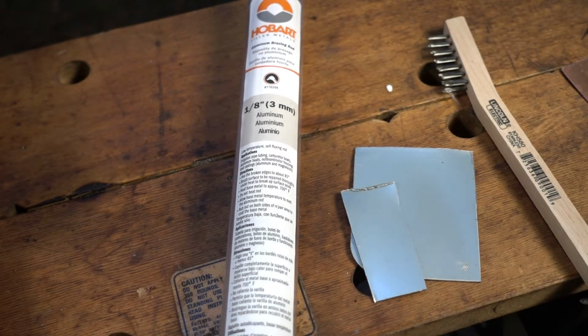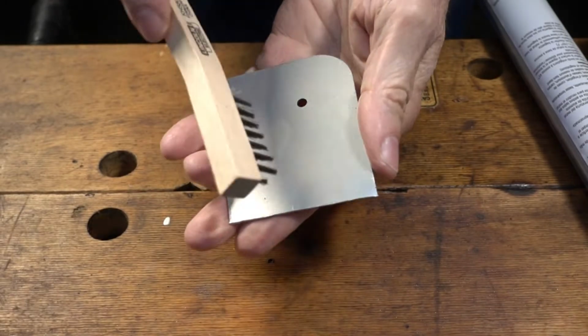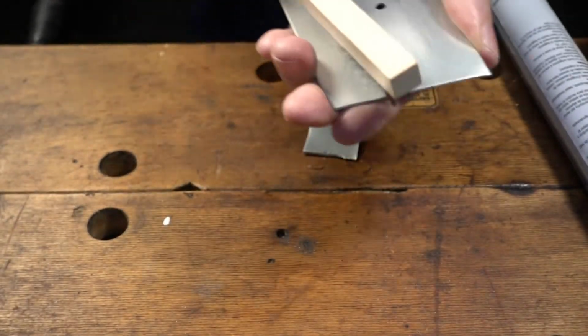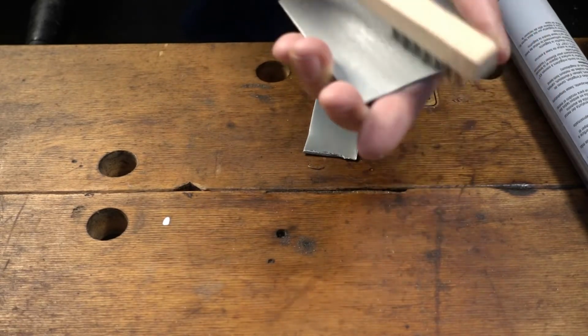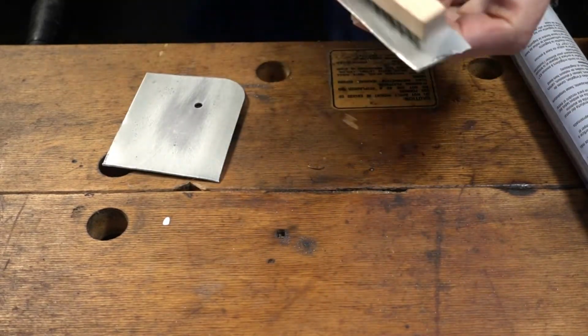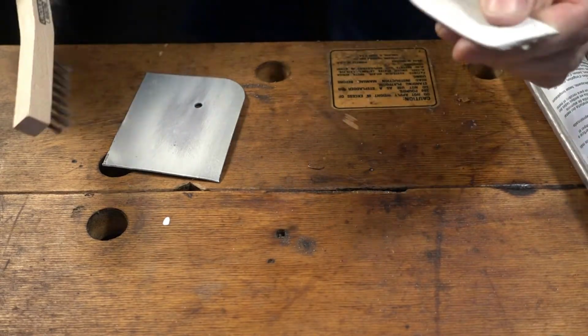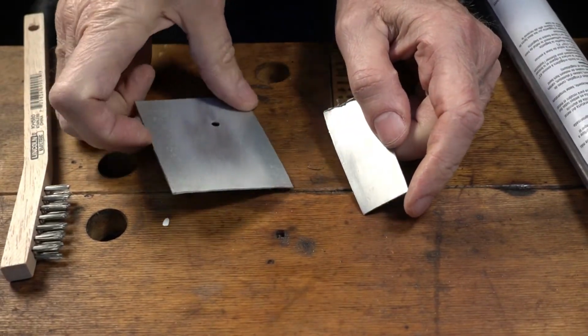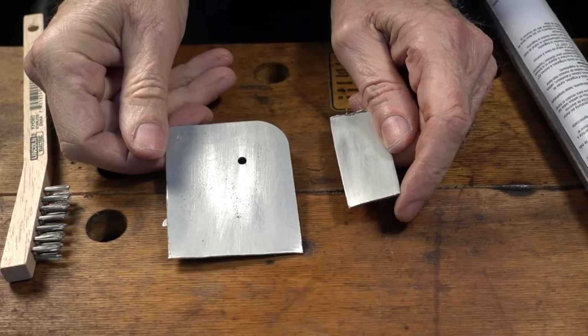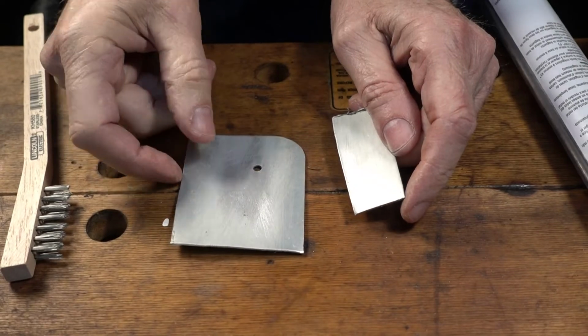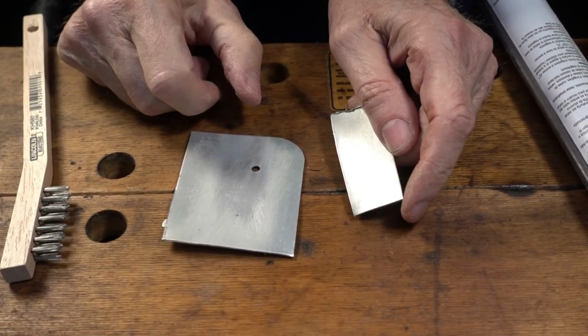I'm not going to take any chances, so I will be brushing the oxide off the aluminum, and then I'm going to clean it off with some acetone to make sure there's no oils in there, which will give a good bond. So once I use this brush, it's going to be dedicated for aluminum only and nothing else. By the way, if you brushed your aluminum yesterday and you're going to weld or braze the next day, you're going to have to brush it again because this oxide layer comes back almost immediately.